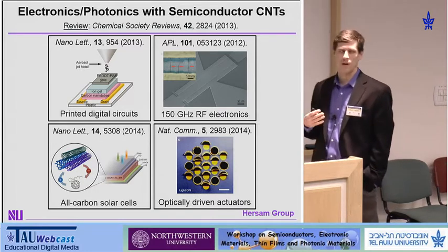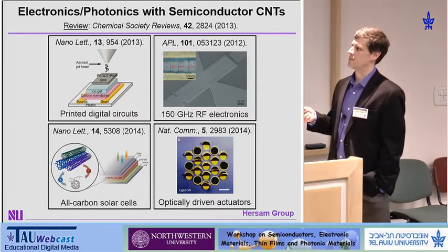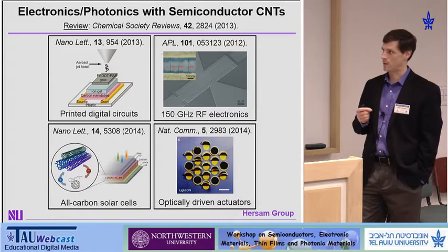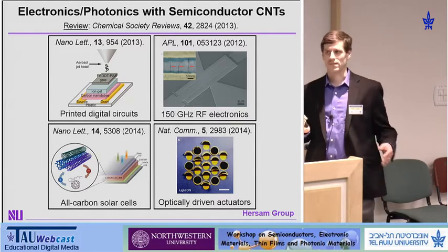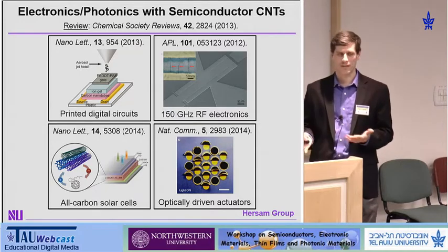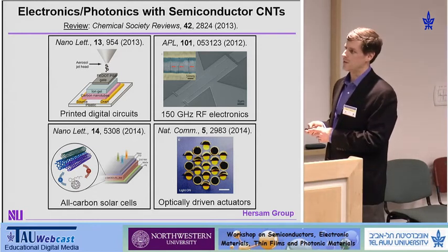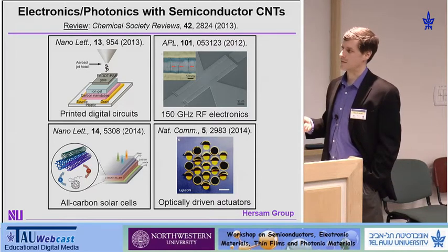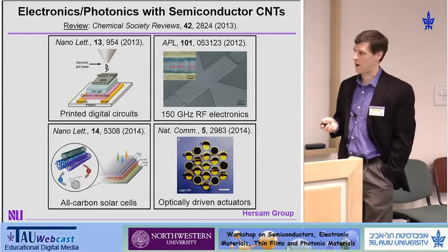On channel lengths in the sub-100 nanometer regime, you get ballistic transport across the channel, allowing very high performance — frequencies of hundreds of gigahertz — which is of high interest to industry. Companies like IBM are now considering this for commercial applications. Because the nanotubes are in solution, we can also mix them with other materials to make so-called bulk heterojunctions, analogous to organic photovoltaics. We take a mixture of carbon nanotubes with a fullerene derivative known as PCBM to make an all-carbon-based solar cell. These solar cells with appropriately chosen chirality distribution have set the world record for all-carbon-based solar cells.